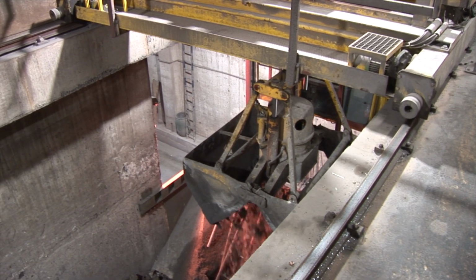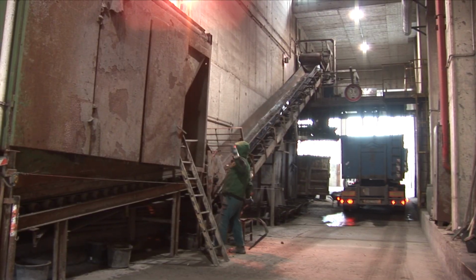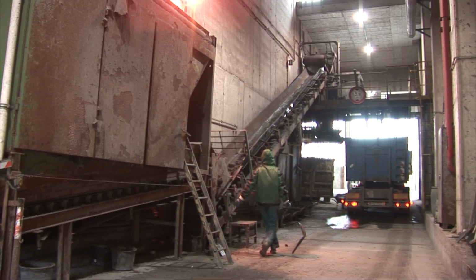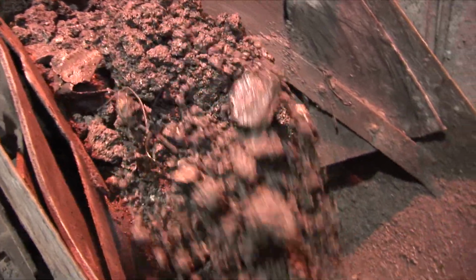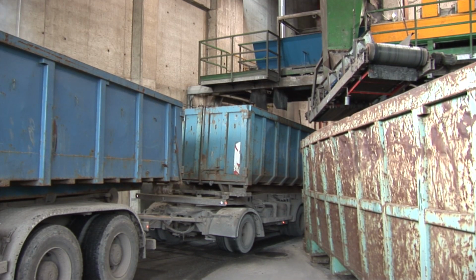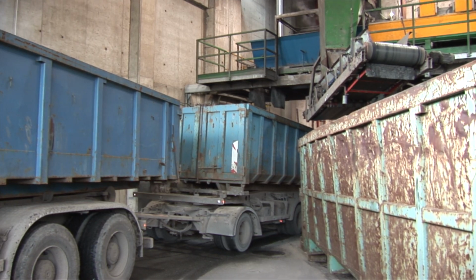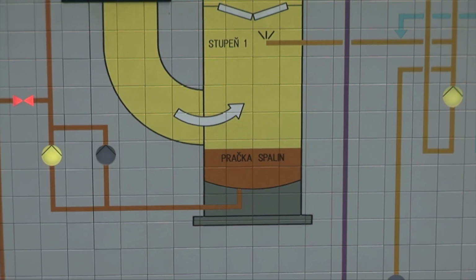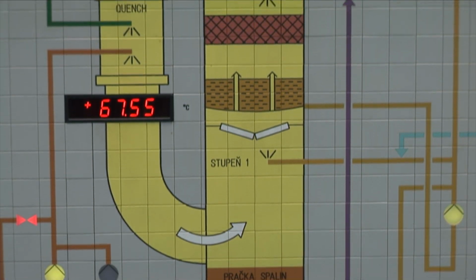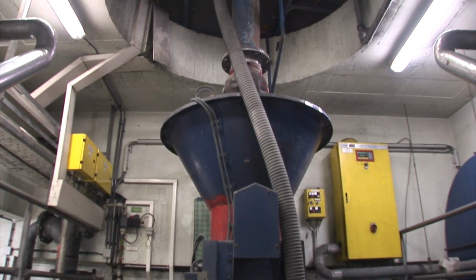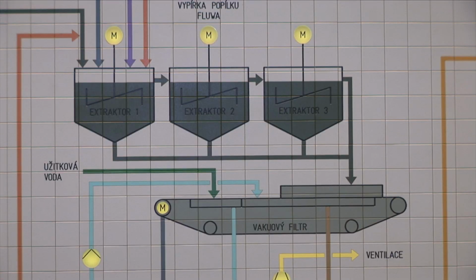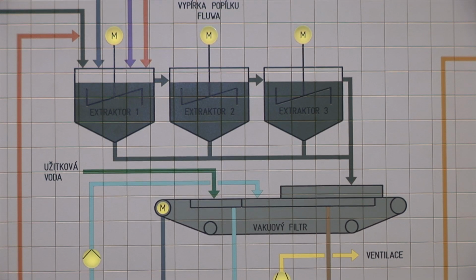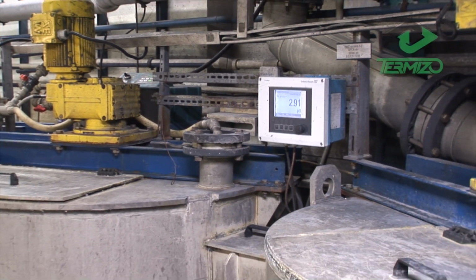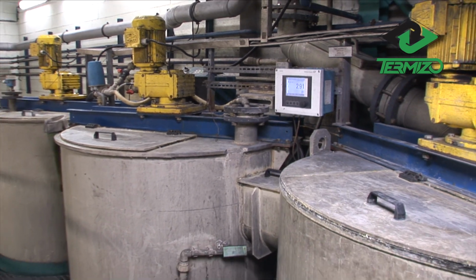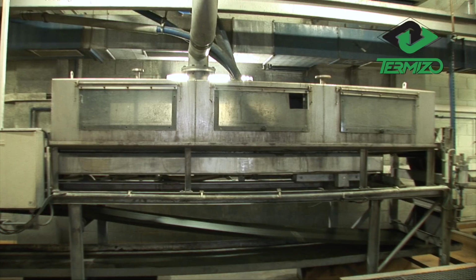So that the raw ash does not indicate any hazardous properties, soluble salts and extractable heavy metals are removed from it using the acidic water coming from the flue gas scrubber, specifically from the first stage, that is, from the quench. The fly ash, which is stored in a silo after its separation from the flue gas, is fed into 3 extraction tanks. Here it is extracted in acidic water with a pH 3.5 at 65 degrees C. The subsequent drainage is carried out on a vacuum filter belt.